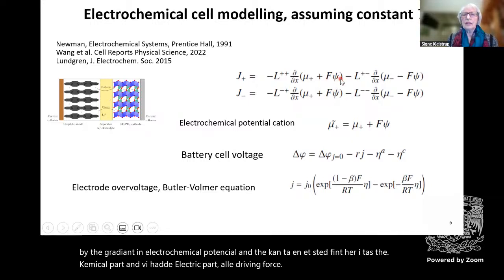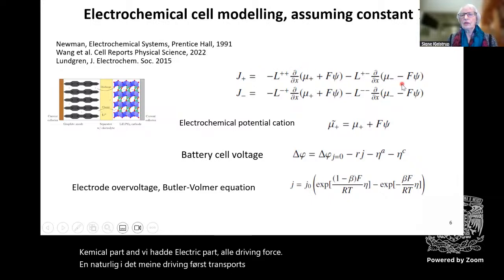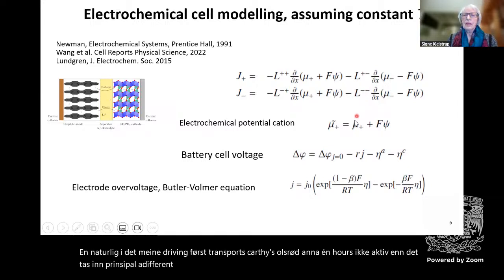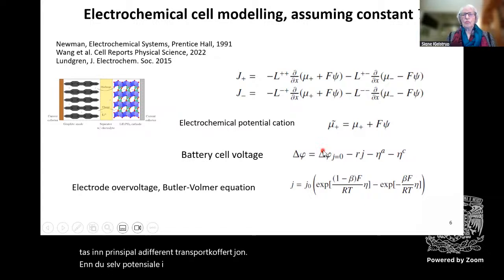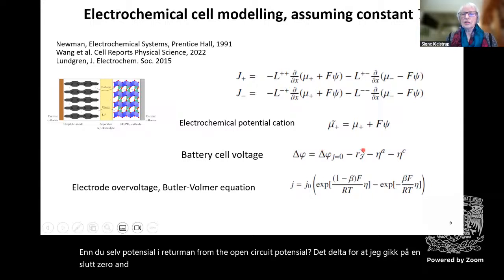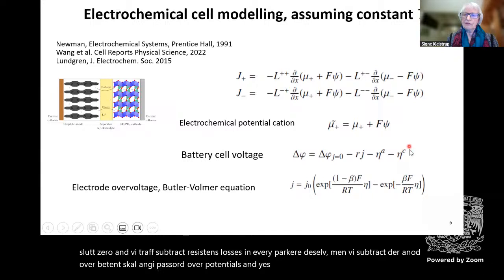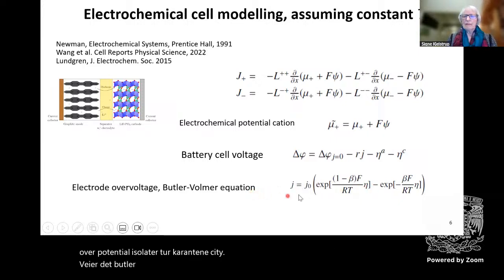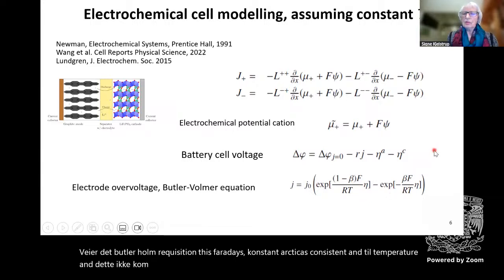And not only the main driving force transports cations, the anion force is also active and has in principle a different transport coefficient. And the cell potential is determined from the open circuit potential, the delta phi at J equal to 0, and we subtract resistance losses in every part of the cell, and we subtract the anode overpotential and the cathode overpotentials. And these I view as resistivities of the cell, that the overpotential is related to the current density via the Butler-Volmer equation, where F is Faraday's constant, R is a gas constant, and T the temperature, and beta is a constant. So this is the common way, and temperature is constant.